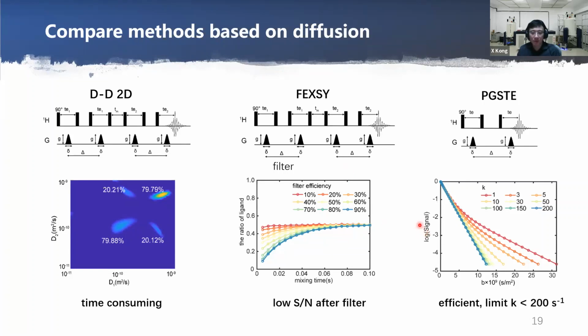Finally, we can use a simple pulsed gradient stimulated echo, PGSTE, experiment. With careful adjustment of the experimental parameters, we can measure the exchange with only two sets of experiments. One is with a very short mixing time, and one with a longer mixing time. Because of the requirement of the gradient pulse, the upper limit for the measurable exchange rate is about 200 Hertz.